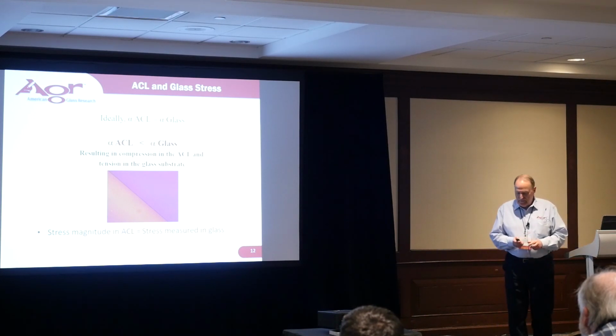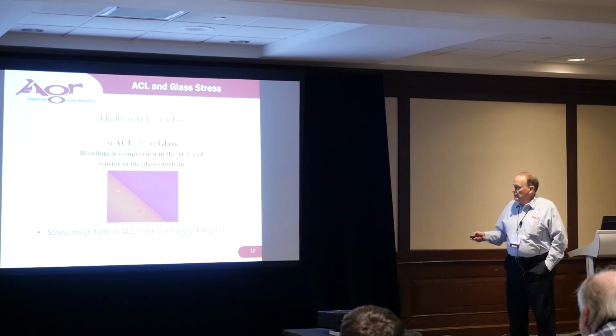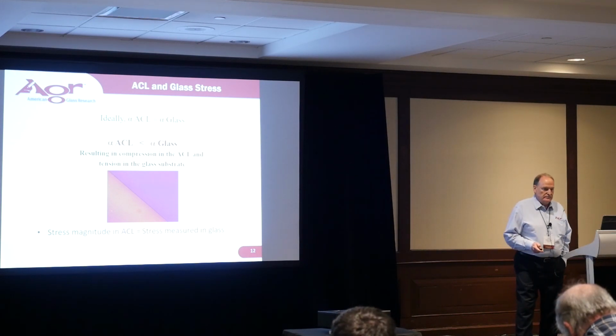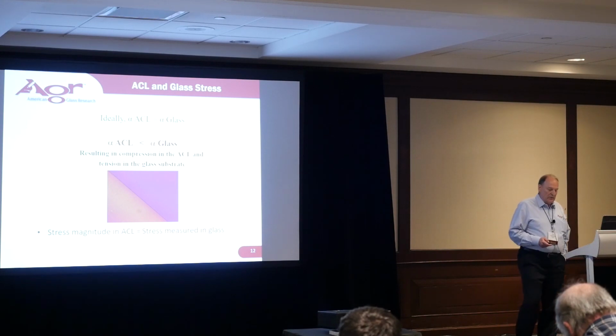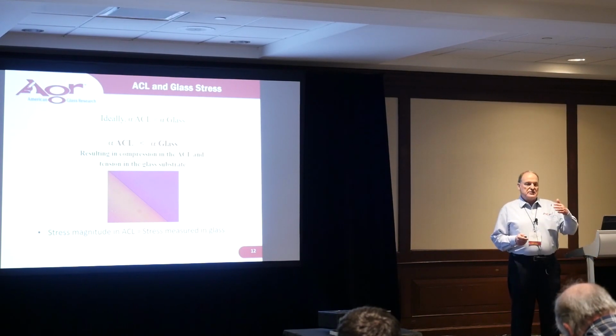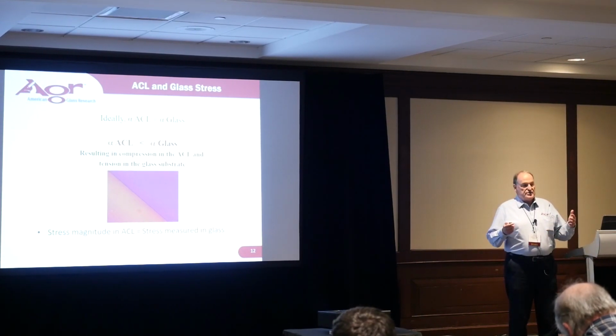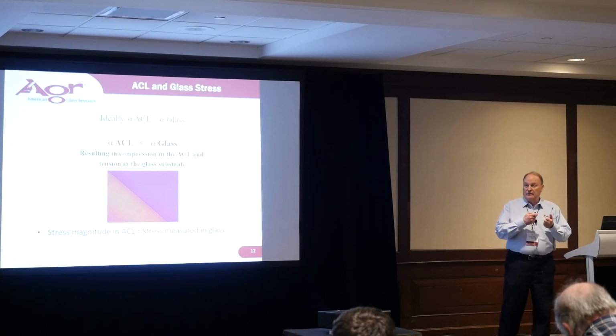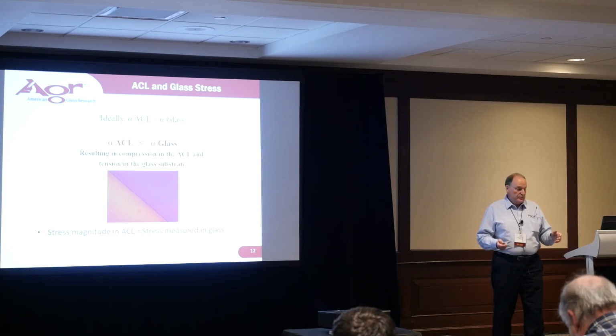So if you know that you're going to have a mismatch, the way that mismatch is supposed to go is that the coefficient of expansion of the ACL should be less than that of the glass. And that's what we've depicted here by that example where we see a tension stress in the glass, we know we have compression in the ACL. The idea here is that we don't want to put the ceramic label into tension. That's a tension stress that's exposed to the world, and is subject to becoming damaged through contact of labeled bottles during use.